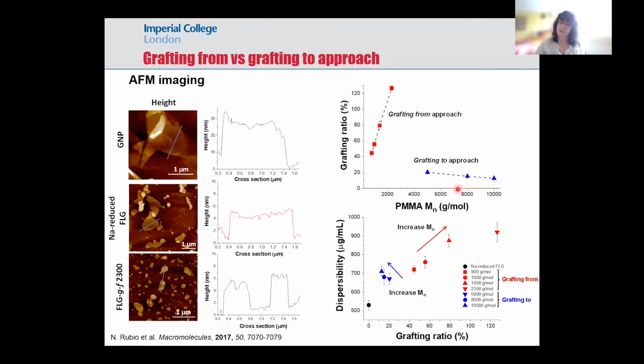And similar in terms of dispersibility, we are comparing dispersibility in acetone versus grafting ratio. As we increase the grafting ratio, for the grafting-from approach in red, we observe an increase in the dispersibility. We are increasing the amount of PMMA on the surface, so the layers are separating more and getting better dispersibility. In the case of the grafting-to approach, the three samples were not significantly different.